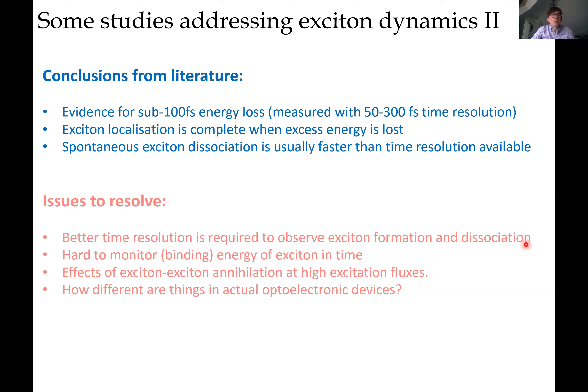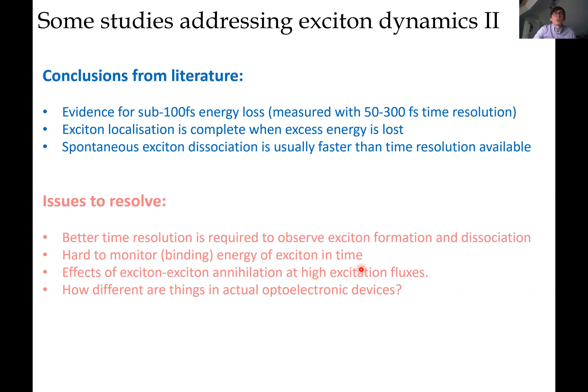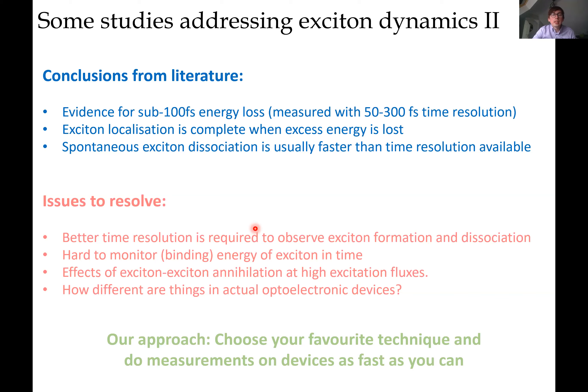However, most of these methods are blind to very important properties of exciton dynamics. Most have about 100 to 300 femtosecond time resolution. It's very hard to say exactly what the energy of a state is — whether it's a bound state or a localized state, or independent electron and hole. There are also exciton-exciton annihilation effects which can mask what we want to know, and the question remains what happens in an actual optoelectronic device, since most studies were done on model films or solutions.